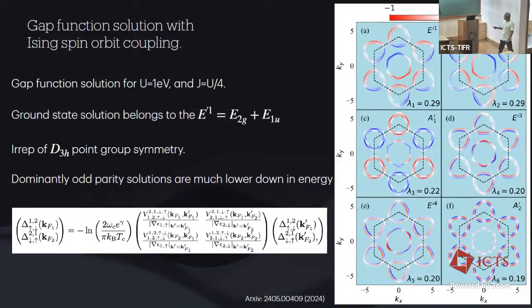Now, if you were to consider, let's say, the same Coulomb interaction parameters and switch on the spin-orbit coupling and actually solve this big matrix, where without spin-orbit coupling these were negligible, then effectively you find the solution actually changes significantly, which is quite surprising. The dominant solution primarily belongs to what is called the two-dimensional E prime representation. I don't call it E2g or E1u because effectively this is the D3h point group that we are dealing with with spin-orbit coupling. And the ground state energy, because of the two-dimensional representation, is twofold degenerate, right? There are two solutions that come out for the lowest energy solution. So it seems that the dominant solution is like this, and naturally an E prime representation for D3h automatically mixes the E2g and the E1u solutions of the superconducting state. How much is the mixing is a different question.